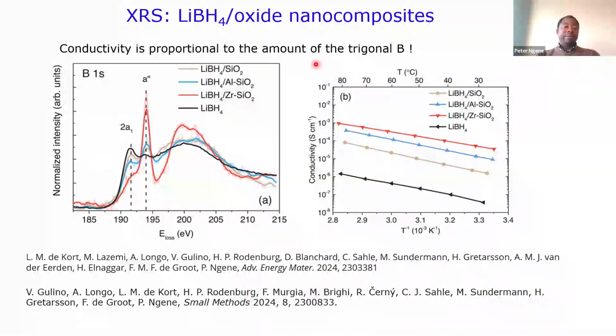So if this surface area or pore volume or even pore size is the determining factor for the conductivity, then you are just comparing apples and oranges. So in this case, we try to keep the surface area the same. We only modify the surface with these materials. And indeed, we can see here that if we just use this as the active material, so this is the interface composition here, when we quantify the amount of this interface composition, it scales with the conductivity we have.